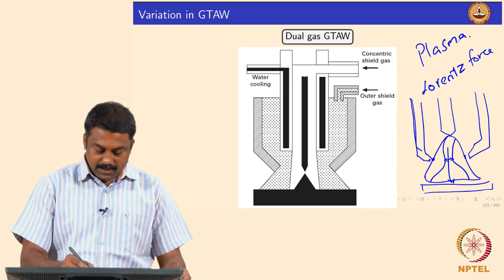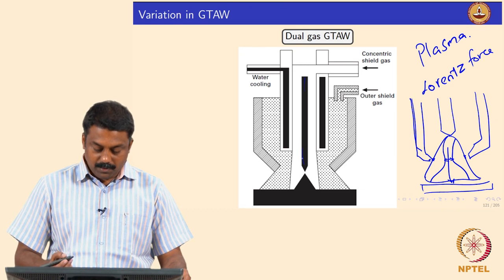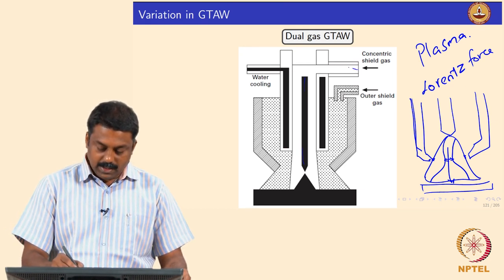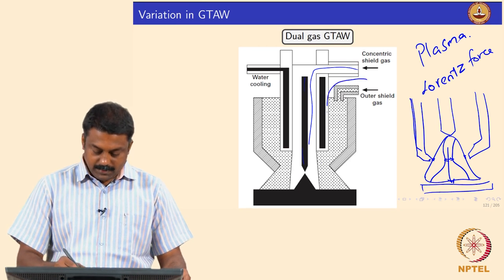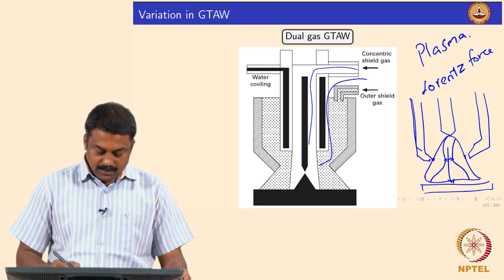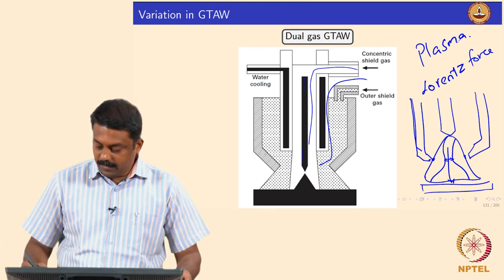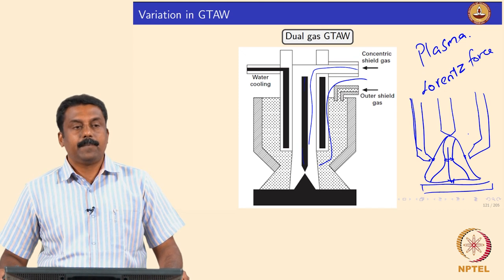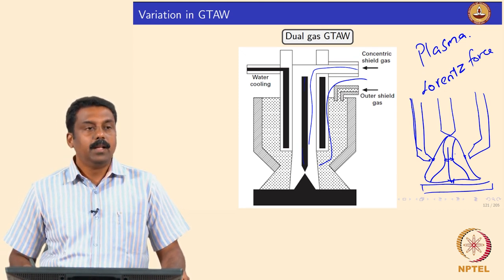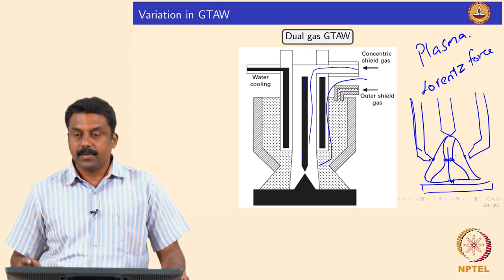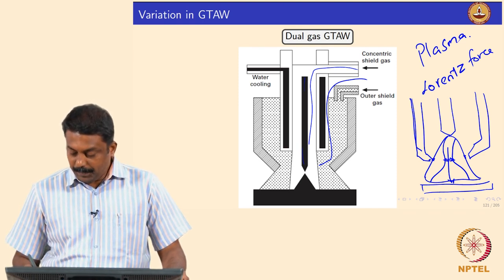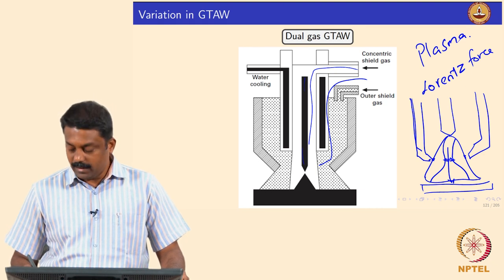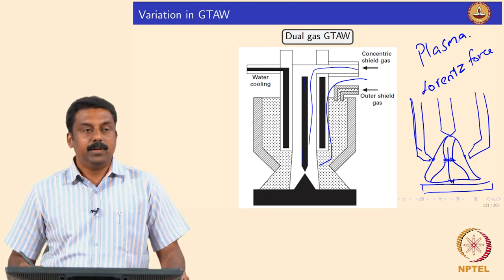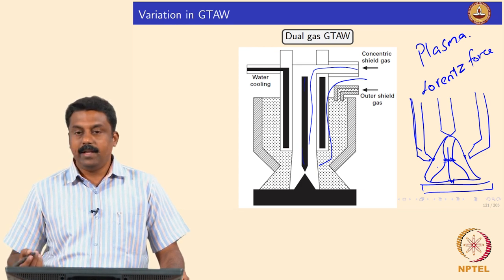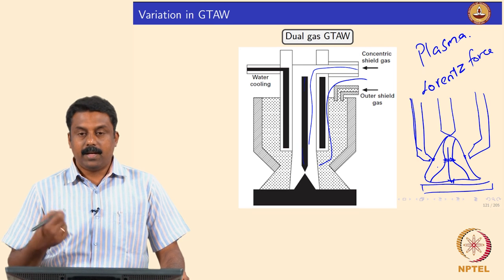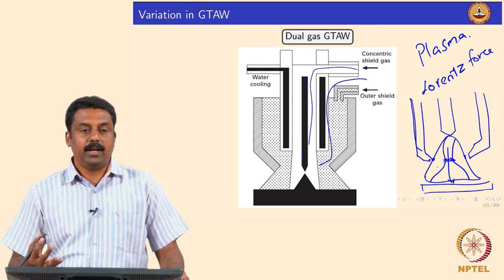So we have a conventional TIG electrode, a tungsten electrode, and you send a shielding gas, and then an outer shielding gas. This is sent in such a way that we cool the arc envelope at a given location, and that can lead to arc constriction. The moment the arc is constricted or shrunk, we pack the fundamental energy carriers like electrons and ions in a very narrow region, and they collide and interact, generating much more heat and energy for further ionization, and then they can get neutralized.